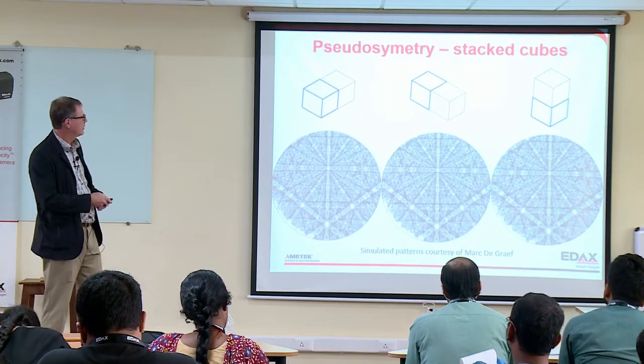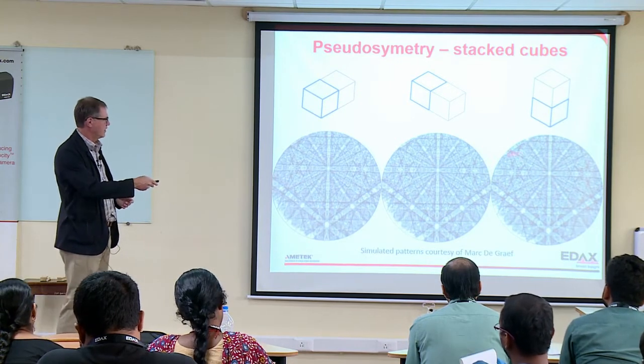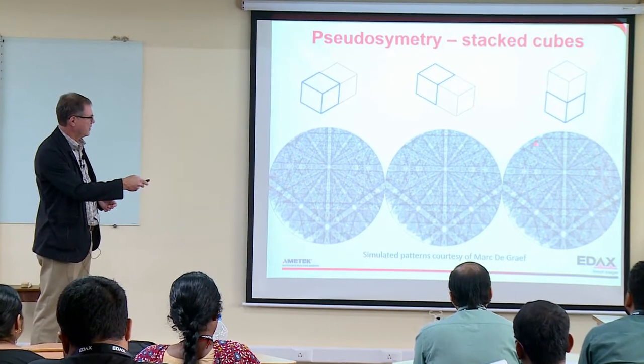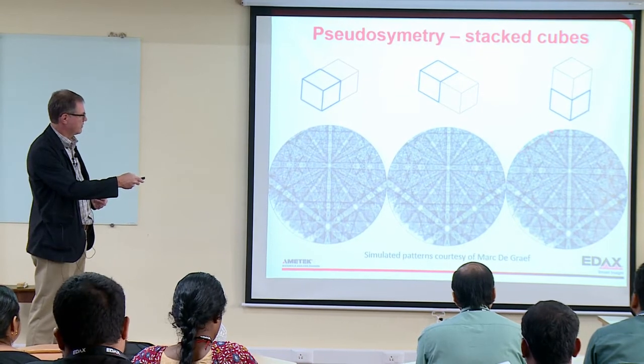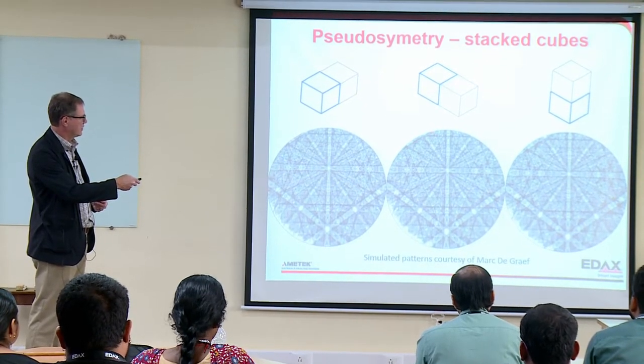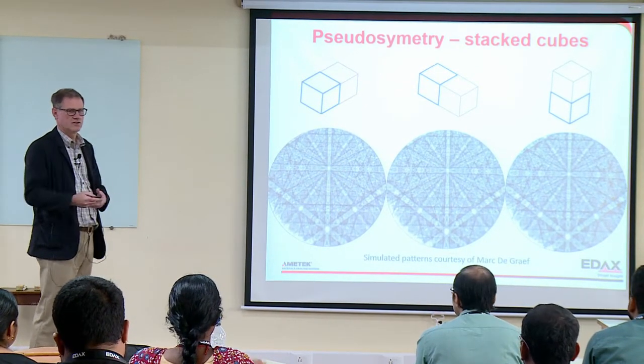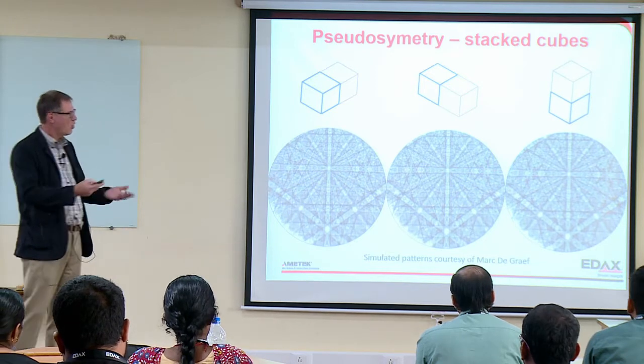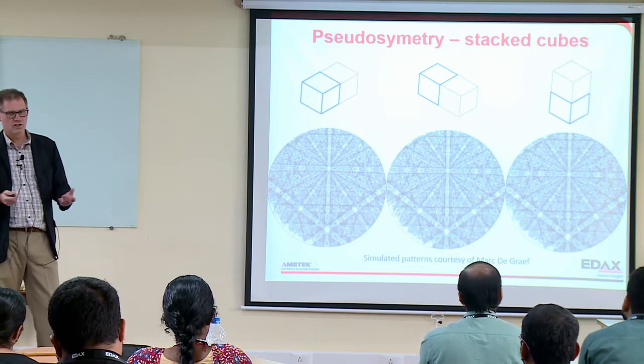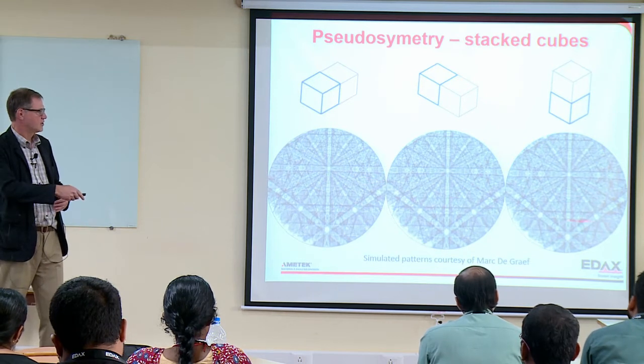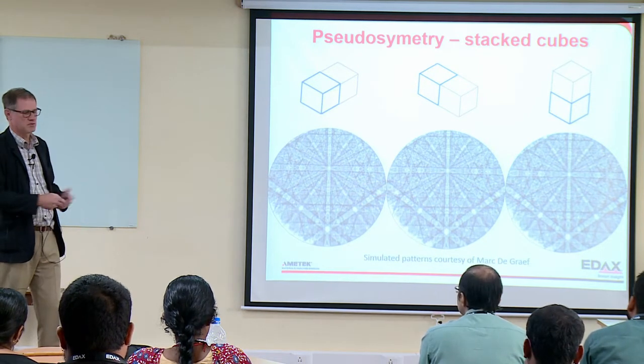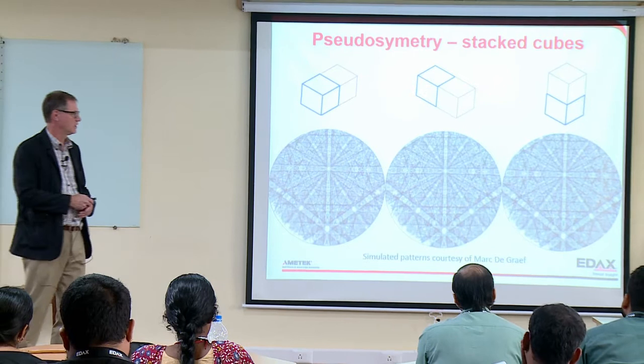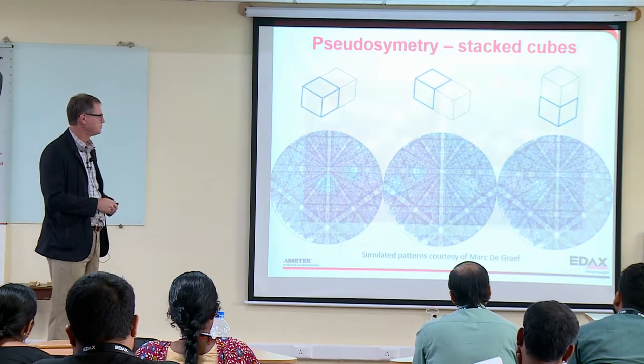If you look really close, you can differentiate these, especially if you look at these two. If you look at this little band up here near the top, it's really close to the edge here and a little farther interior here. So there is some hope you could differentiate these, but usually the patterns, these are simulated patterns, and the patterns from this material are usually not very good. So it really becomes impractical.